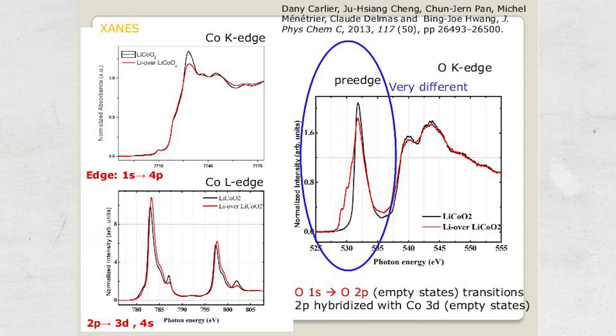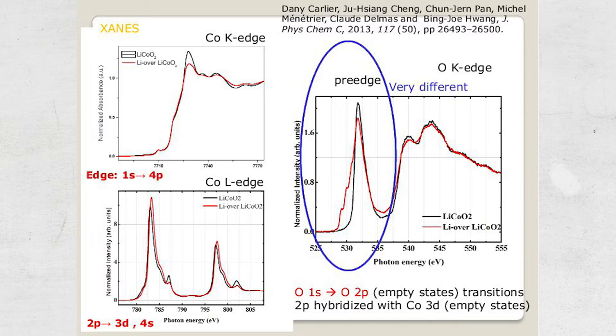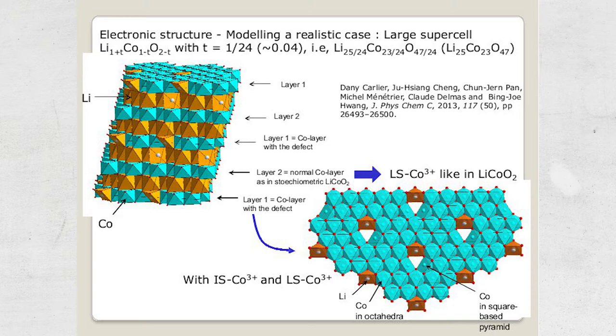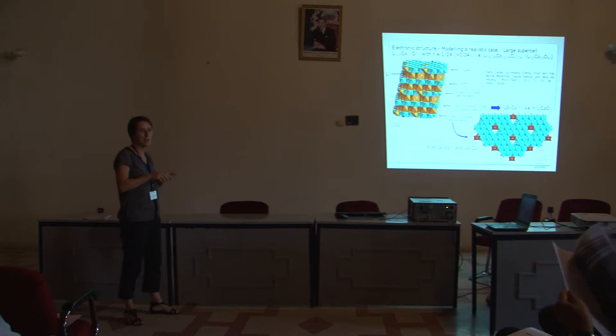At the cobalt K-edge and cobalt L-edge, the shapes are not very different. The main difference was observed at the oxygen K-edge: for the over-stoichiometric LiCoO2 (red curve) we observe an additional feature at lower energy. We used a supercell with diluted defects — Li₁₊ₓCoO₂ — where one layer out of two is a normal layer like in stoichiometric LiCoO2, and in the other layer we introduce some defects, meaning only two cobalt ions are in a square-based pyramid while the other cobalt remain in normal octahedral sites.